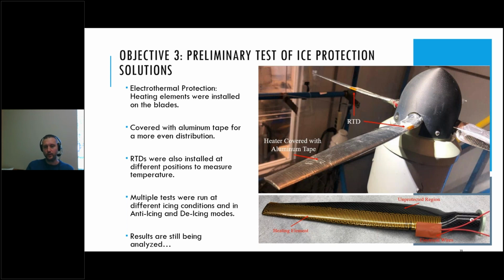So in anti-icing, you completely prevent any ice from accumulating, while in de-icing, you allow a certain amount of ice before you turn on the electrothermal protection. Then the ice sheds because you melt the interface between the blade and the ice layer, and then you shut it down again, and you wait for a new accumulation before turning on the system again. So the results are unfortunately still being analyzed, so I cannot present them right now. Next slide, please.